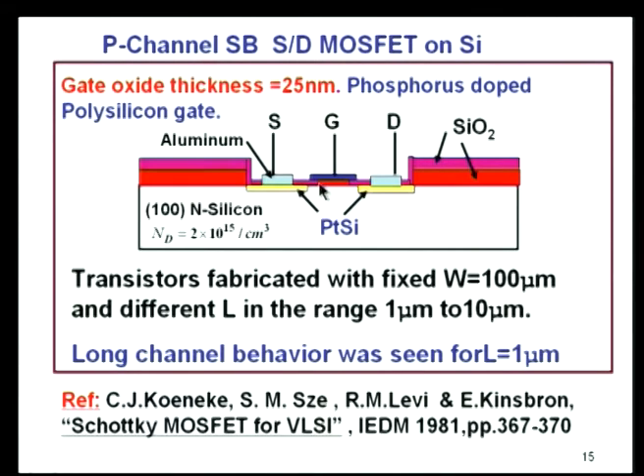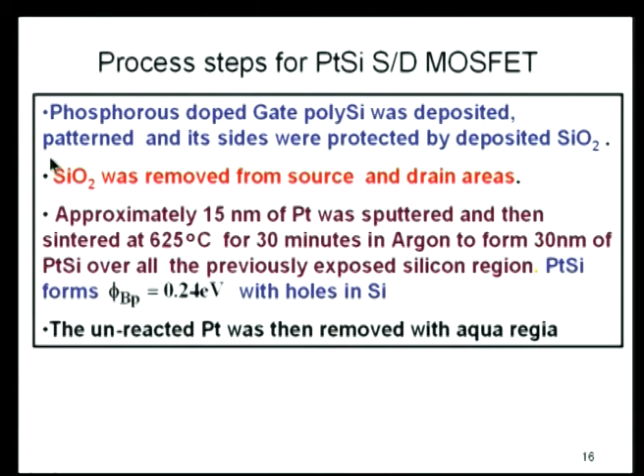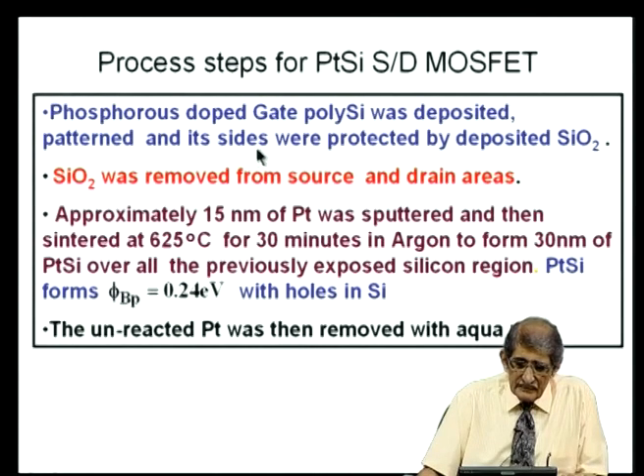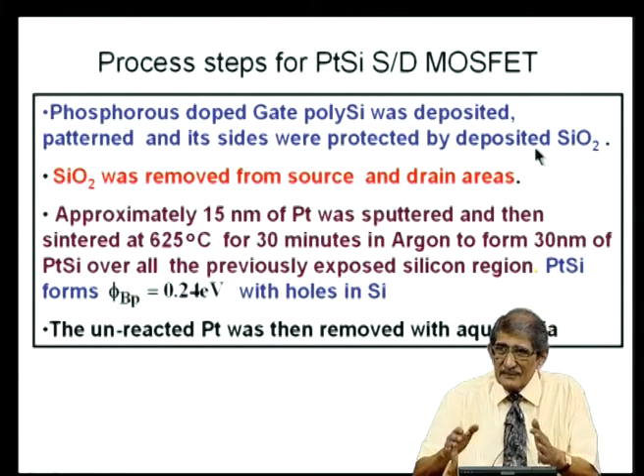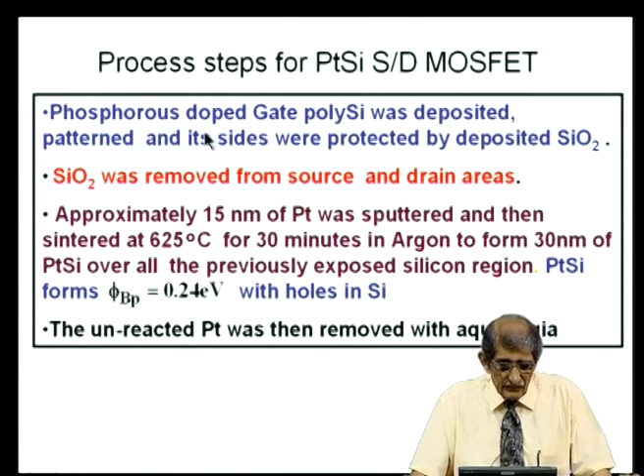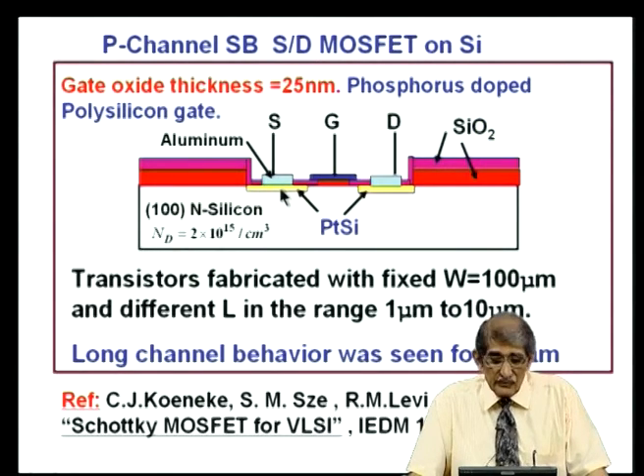They made it with the same approach, gate oxide about 25 nanometers. We are talking of 1981. So gate oxide of 25 nanometers and a phosphorus doped polysilicon gate; I have shown it as metal, but they used phosphorus doped polysilicon. The transistor width was W and the channel length was L, 1 micron to 10 micron, various lengths, and long channel behavior was seen for L equal to 1 micron. The substrate is N type silicon, 10 to the power of 15. Phosphorus doped gate polysilicon was deposited and patterned, and its sides were protected by deposited SiO2. First the gate was decided, sides were protected. SiO2 was removed from source and drain regions, where you want to put the contact.